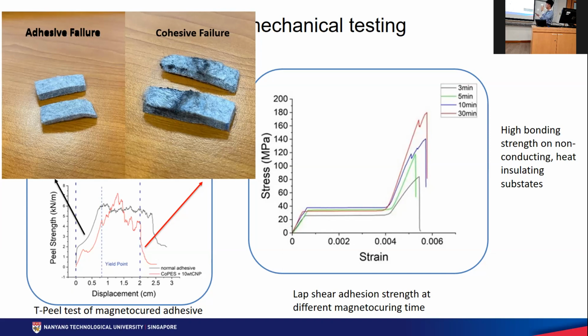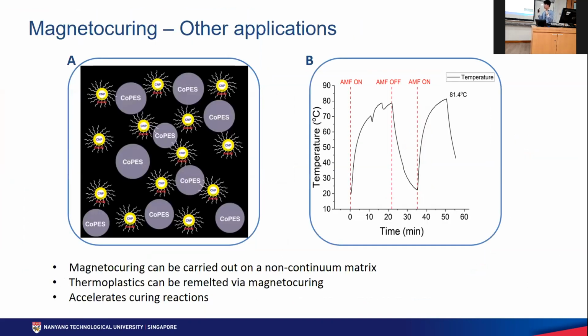Essentially, magnetocuring can be used to obtain very high bonding strength on non-conducting heat insulating surfaces. So I've been talking about how we can disperse these nanoparticles in a liquid resin matrix. However, recent works have also found out that, when you look at the scheme on the left, magneto curing can be carried out on thermoplastics.